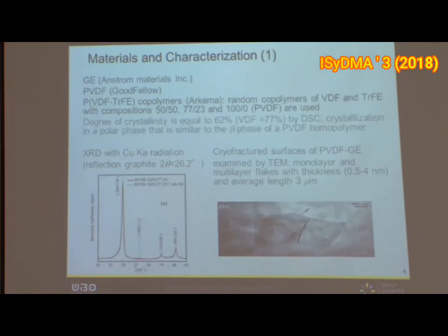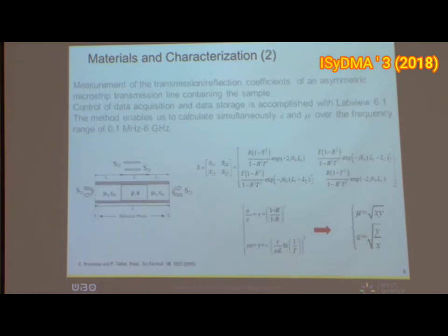Okay, so basically the materials are graphene - if you put a cryofracture surface of this sample in TEM, you get flakes with typically 1 nanometer thickness and a few microns in size. X-ray diffraction shows that you don't have any contaminant in the system, and you find the PVDF peaks and also the graphene peak, which is related at 26 degrees.